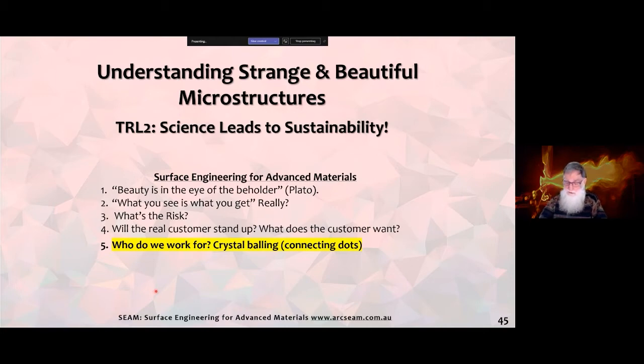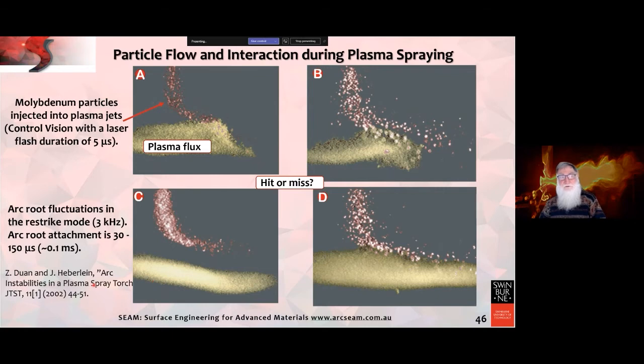So who do we work for? And let's think about the future. First of all, we must understand how these particles interact within the thermal flux. And by taking video images at very high speed, we're able to see that, say, moly particles, and this is old work, but it's still relevant, by Professor Heberlein. What we find is that some particles enter the region, look at A and B, and some particles don't. Some particles miss it, look at C, because the arc is fluctuating at 3 kilohertz. So it's kind of hit or miss.